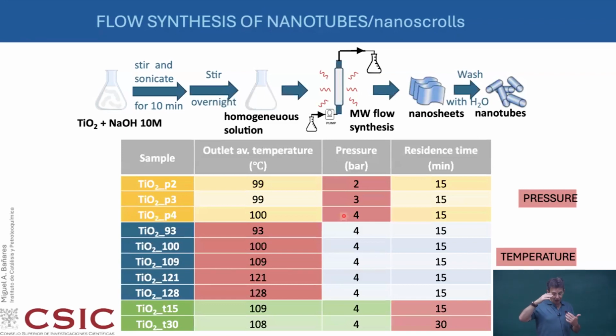So you can go at high pressure, controlling the pressure, which is good because then you can go at more than 100 degrees without boiling, because if things boil, the efficiency of microwave is killed. But if you are dealing with 2, 3, 4 bars, it will not boil at 110, 120 degrees C. That allows you a much more efficient process.